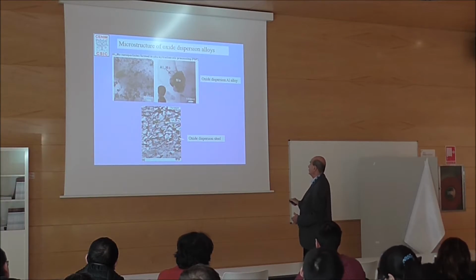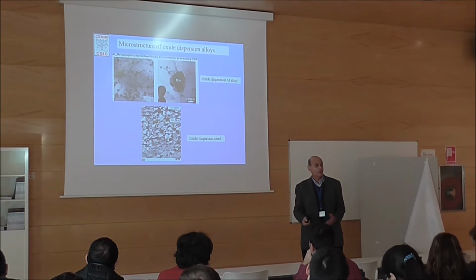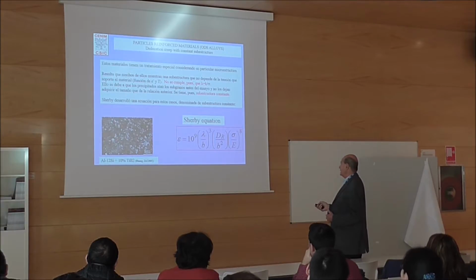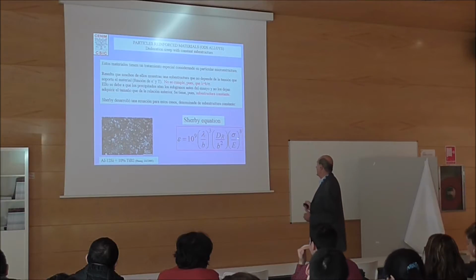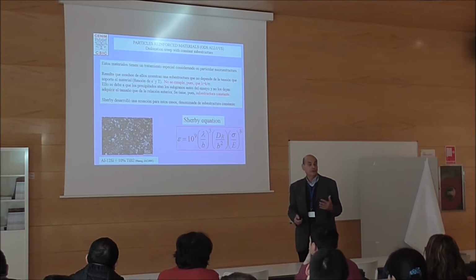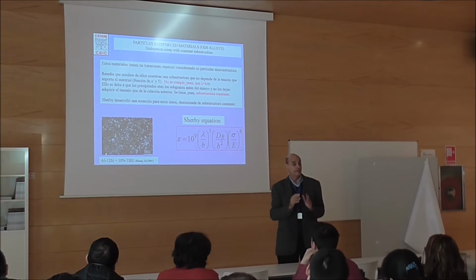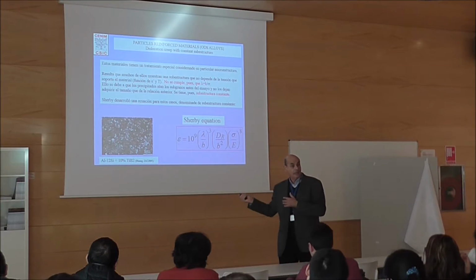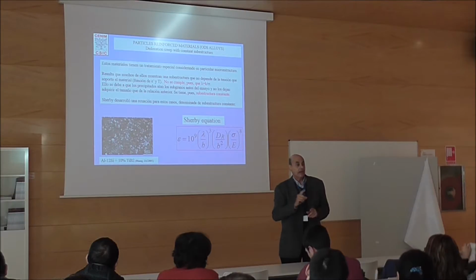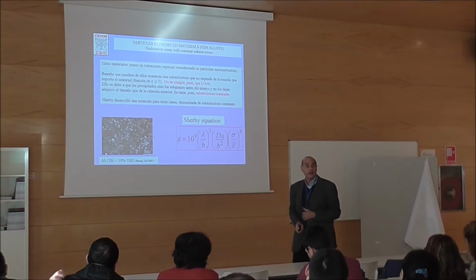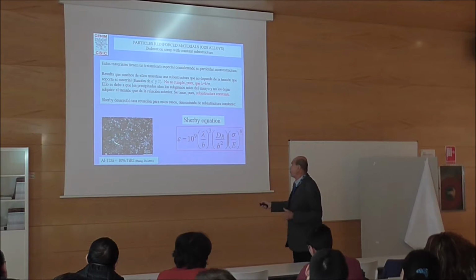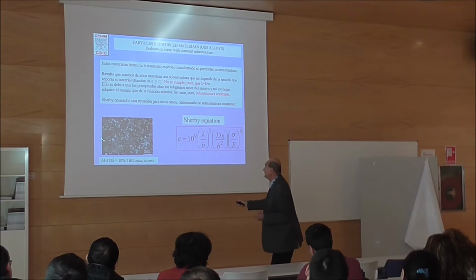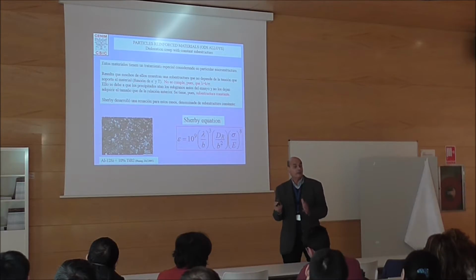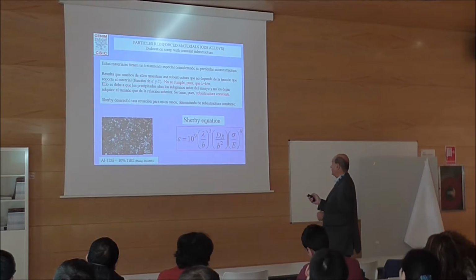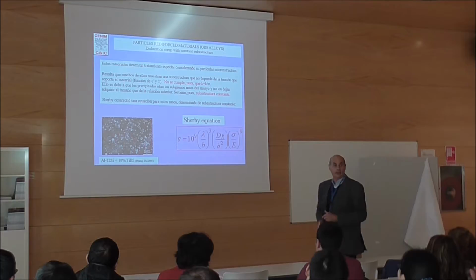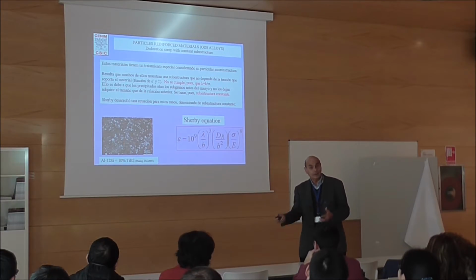precipitates, for instance, nanomaterials, oxide dispersion alloys, for instance, and this is steels. What happens with the microstructure? Does the same thing apply? The answer is no, because this equation with n equals 5 is not fulfilled, because the substructure is not changing. So it's a fundamental thing. We have slip creep with changing microstructure, n equals 5. Slip creep where the subgrains are not changing, then we have n equals 8. And why are they not changing? Because when we change the stress, the subgrains formed at the beginning cannot vary because they are tied by the precipitates. They are a constant subgrain structure. And that's why it's called dislocation creep with constant substructure. So it's another type of slip creep mechanism.